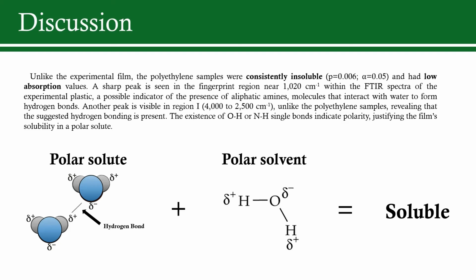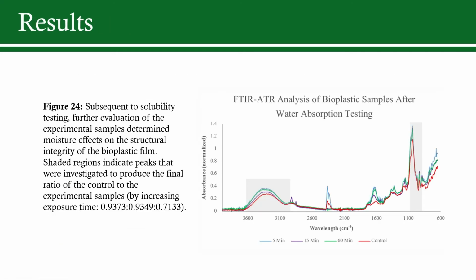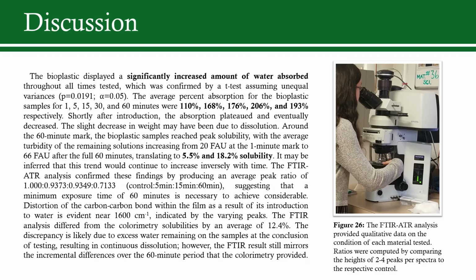Nitrogen and hydrogen, or oxygen and hydrogen bonds are polar. Using the principle that like dissolves like, it is understandable why the bio-based plastic is soluble. The FTIR spectra analysis of the bioplastic after exposure to water revealed that there was some distortion of the carbon bonds. The solubility values for the bioplastic obtained from the FTIR analysis differed by approximately 12.4%. The reasoning for this may be that some residual water was left on the sample strip after the testing concluded, leading to continuing dissolution. However, the general trend of solubility over time is the same for both methods.